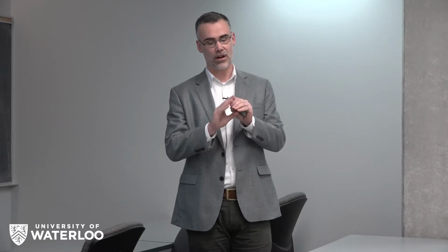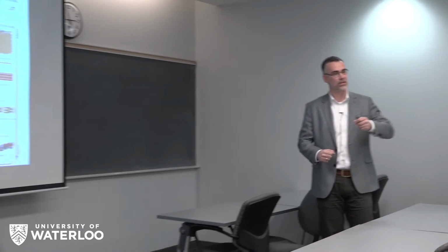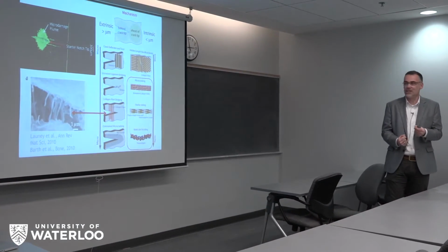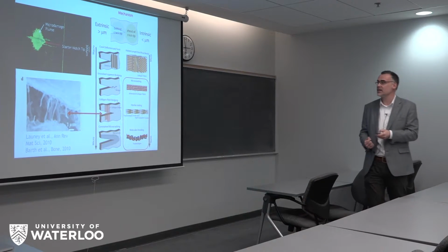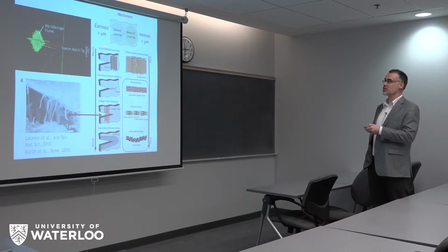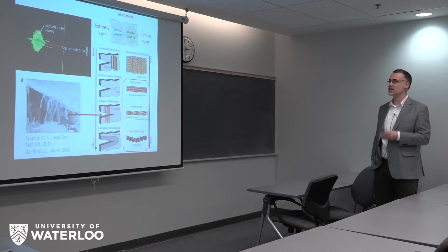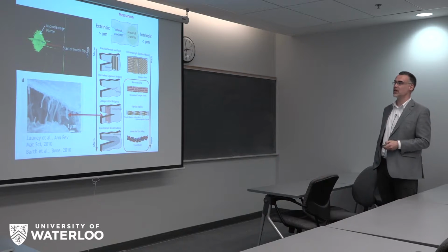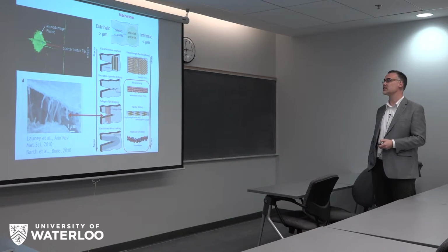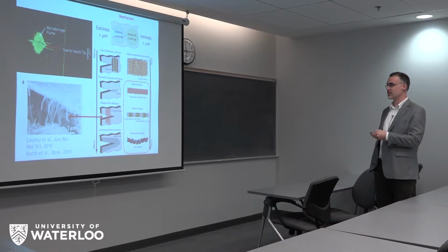So what we call intrinsic ahead of the crack tip and extrinsic behind the crack tip. And they act at different scales. I already mentioned microcracking and plastic deformation ahead of the crack tip. And then we also see mechanisms like collagen fiber bridging behind the crack tip. These apply tractions, basically apply stresses, that steal energy and driving force away from a crack tip under load. Also very significant is crack deflection. As the crack changes direction, the driving force to grow that crack changes. And so bone has all these mechanisms at play.